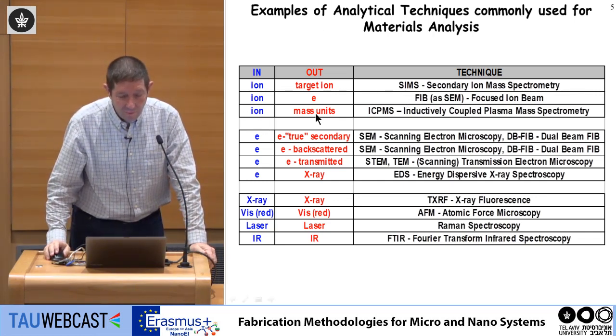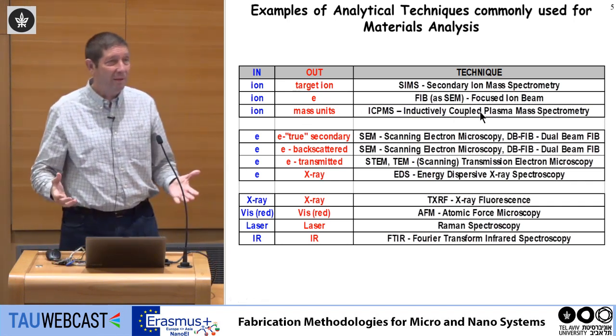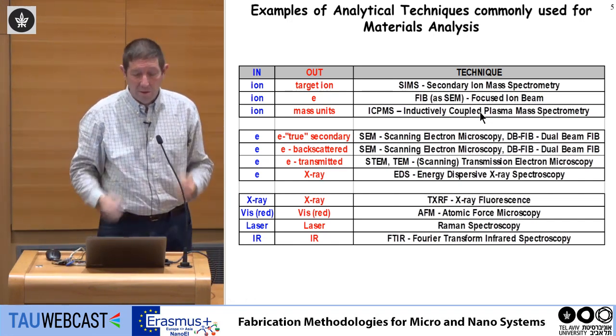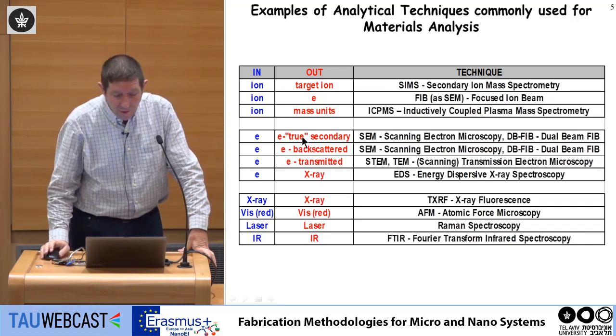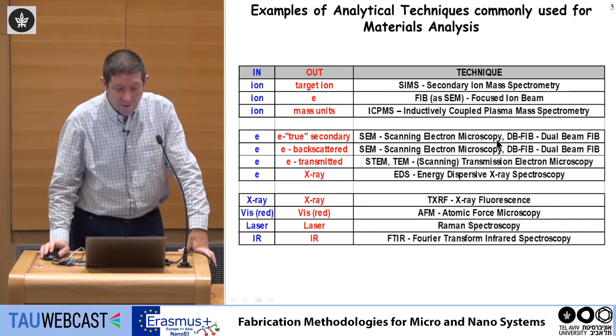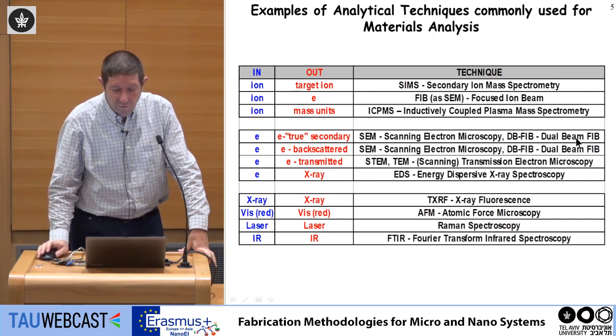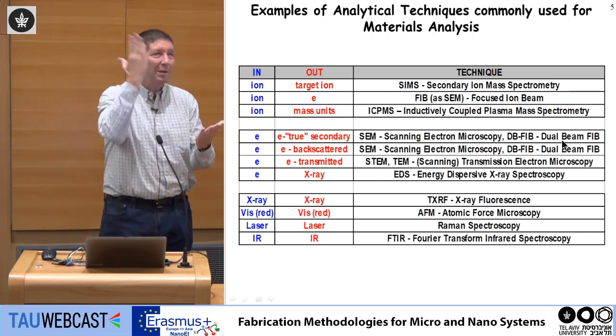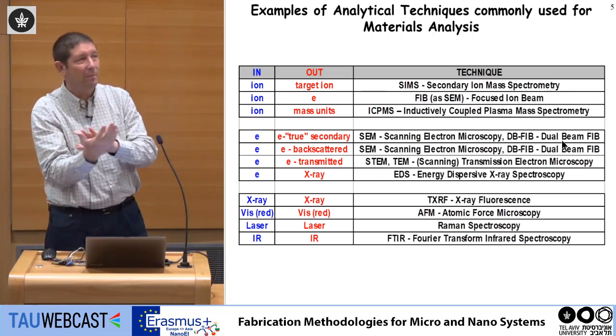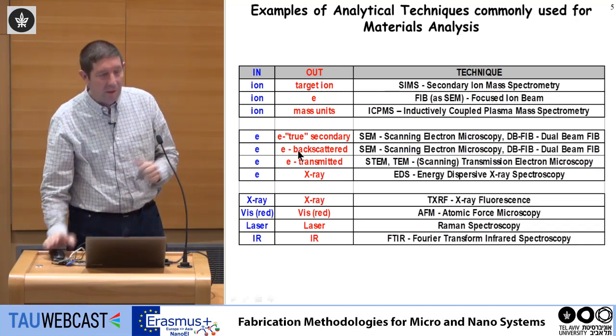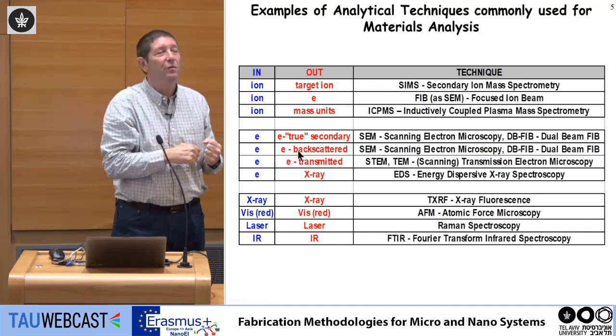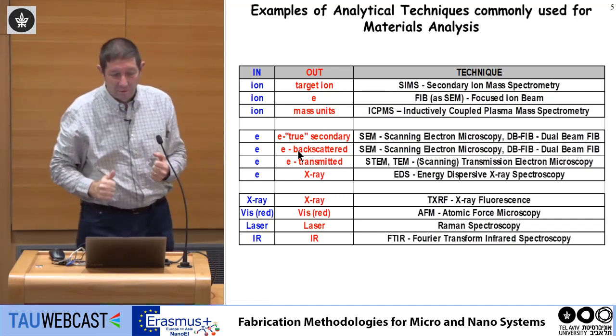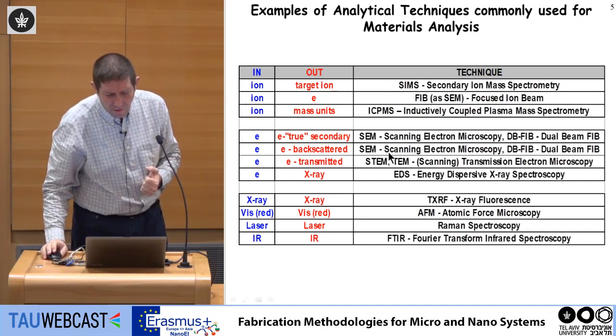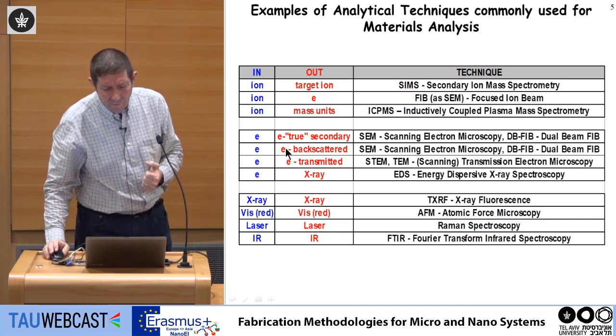I can apply ions and practically measure the mass, which is called inductively coupled plasma mass spectroscopy. I apply energy to the system, generate plasma, and look at the emission and measure the mass of the plasma. I can apply electrons and generate secondary electrons, and this is called scanning electron microscopy, or dual beam FIB, which is a focused ion beam, where I use the ion beam to cut the sample and the electron beam to image the sample. Or I can take electrons, and the electron hits the sample, and because of Rutherford interaction, some of them can be backscattered. Backscattered. This is also scanning electron microscope. So this is backscattered electrons.